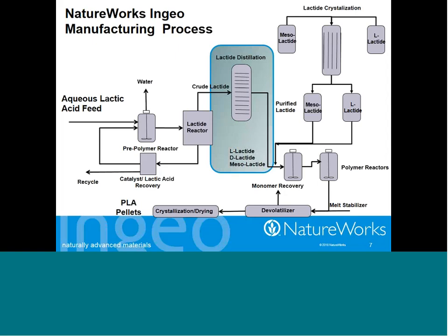The other thing I'll mention at this point and on later slides is the polylactide that we make is produced via a ring opening polymerization. So the molecular weight is determined by the number of chain initiators that flow along with the lactide into the polymer process. So we need to control the number of remnant oligomers that are present in the lactide so that we can make the desired molecular weights.